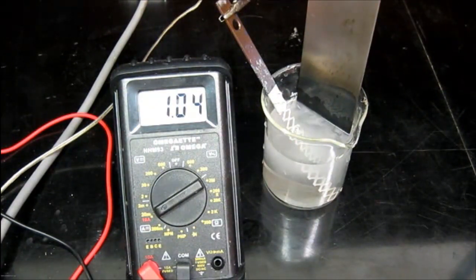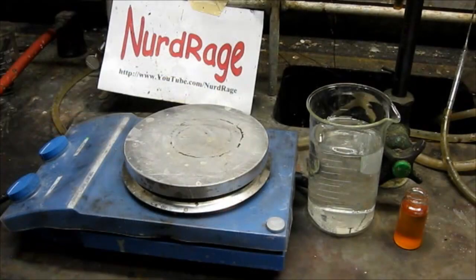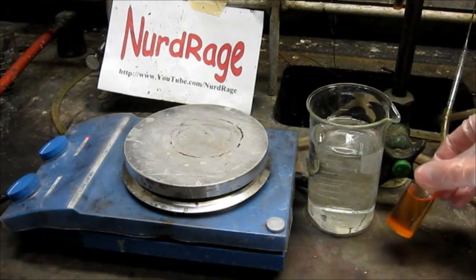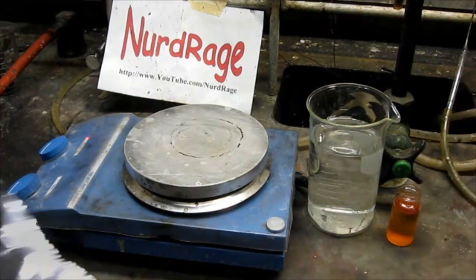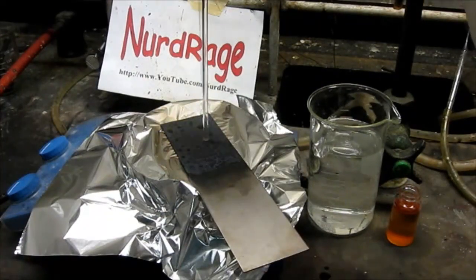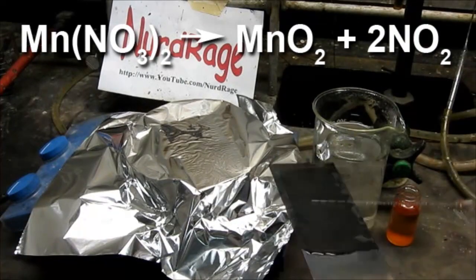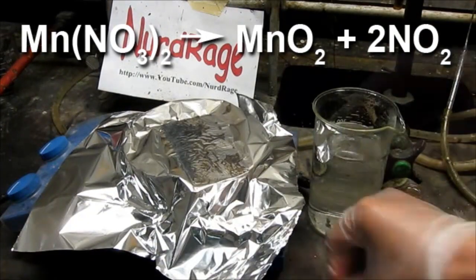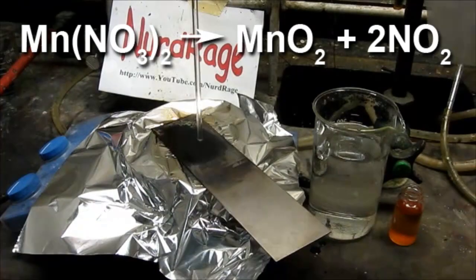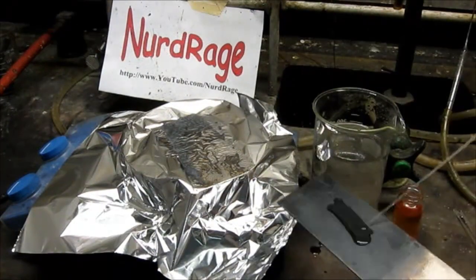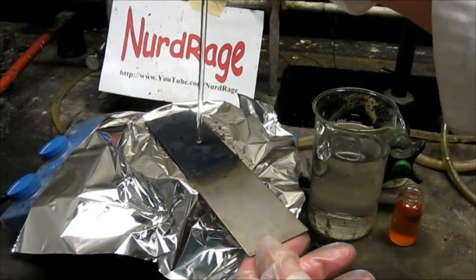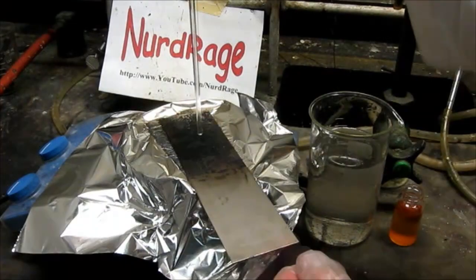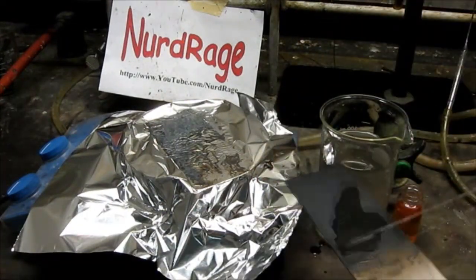To make it last longer, we place an overcoat of manganese dioxide, turning it into a manganese dioxide electrode. To do this, we go back to the hot plate and start applying layers of manganese nitrate. Normally it's pink, but mine is contaminated with iron. This doesn't adversely affect the electrode, however. Using the same techniques as cobalt, we decompose the manganese nitrate onto the surface to make manganese dioxide. You can apply as many layers as you like. The more layers you have, the longer the electrode will last. I'm going with about 5, but I've heard of other people going to 20 or even 50 layers.